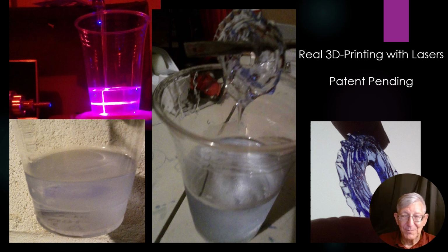But anyway, the point here is really that without the dye in the resin, we would have never figured out what was going on until it was too late. Because eventually you'll get a solid, but it may not be the solid you're looking for. So the dye allows you to very finely tune the amount of energy that you're putting into your system, because it tells you exactly where and how much solidification you have achieved.